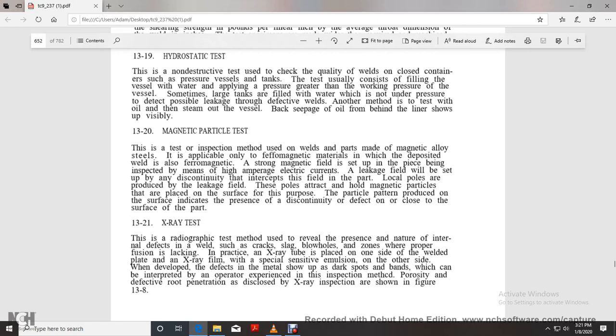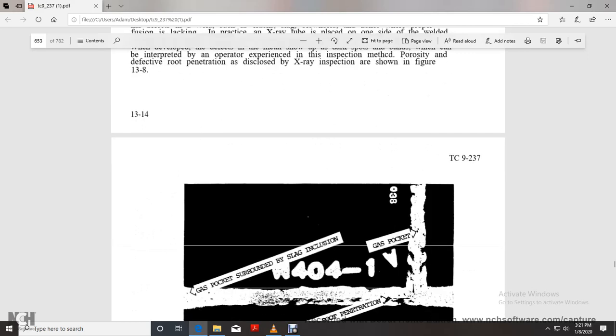Developed, the defects in the metal show up as dark spots and bands, which can be interpreted with operator experience in this inspection method. Porosity and defective root penetration disclosed in the X-ray inspection are shown in figures 13.8.